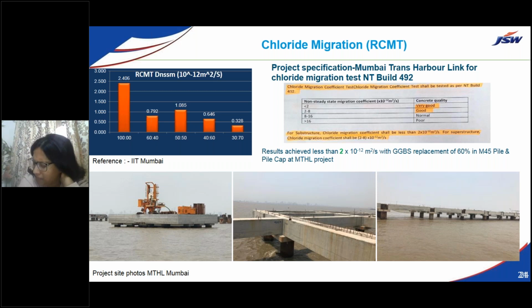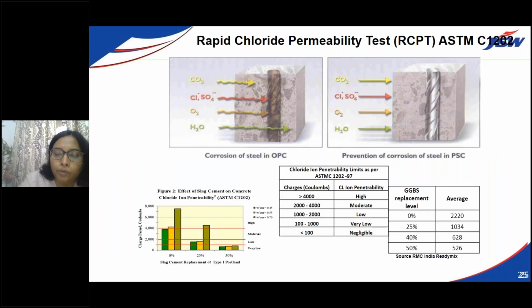So there is a trans-harbor link which is made on the Arabian Sea, and it is going to be some 30 kilometers long, and it is going inside the sea, and it is connecting different parts of Mumbai. So here, if you see this trans-harbor link, we are showing you the photo here. So the contractors are L&T and Tata Projects, and they had done so many trials. They have done, each must have done more than 100 trials each with OPC, OPC fly ash, OPC slag, OPC GGBS, then OPC GGBS microsilica. Each of them had done, and after all doing, we could see only the products of slag. So there, this chloride migration coefficient test as per NT Build 492, which should be less than 2, could be only achieved with GGBS. In this extremely aggressive environment, no other product could take care of this.